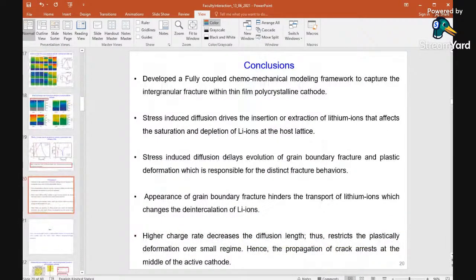So for this structure, what we see from this is that we developed a coupled chemomechanical model for the intergranular fracture, and this is one of the first models which considered bulk and interface as separate thermodynamics. We investigated the stress induced diffusion, which drives the insertion or extraction of the lithium-ion.